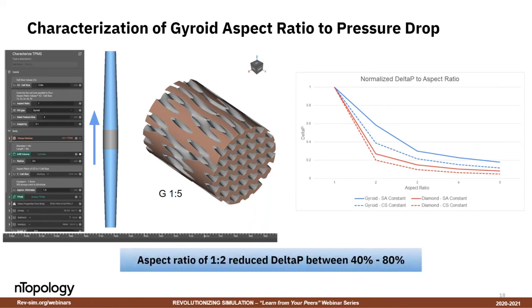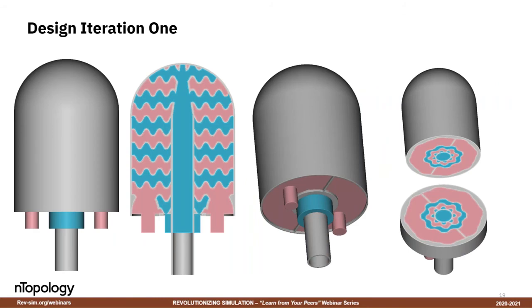And really the main takeaway from this is as soon as we hit an aspect ratio of 1:2 for both the gyroid and the diamond, we saw a reduction in pressure drop between 40 and 80%. So going forward, what I'm encouraging a lot of people to do is immediately hit that aspect ratio of 1:2, keep your part printable, and improve your pressure drop. Now we're going to take these case studies and drive them into our next generation of designs. This is what we're going to keep as the primary topic for this presentation.